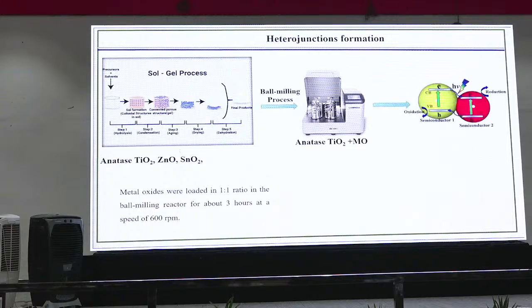So when we did the ball milling, we usually get the heterojunctions like this. One semiconductor mixed with the other semiconductor, we get the heterojunctions, so that I can improve the visible light activity, and even I can avoid the recombination pattern of it. So this is what I expected. So I have taken one TiO2 and one ZnO. I want to generate titanium dioxide of one phase and the ZnO of another phase.